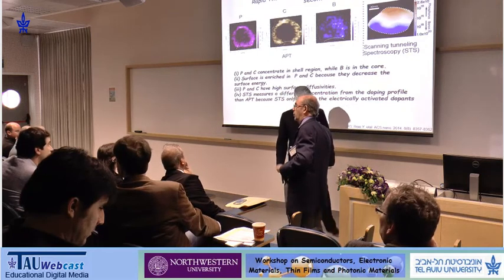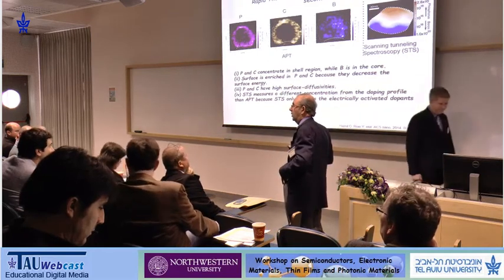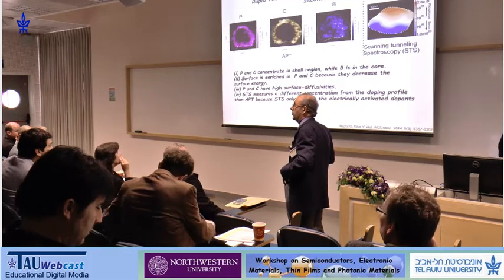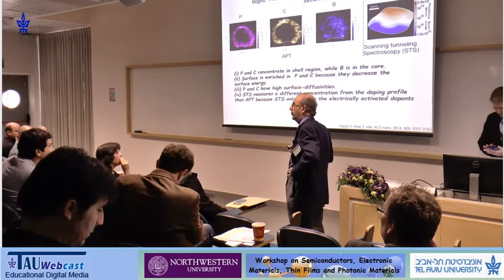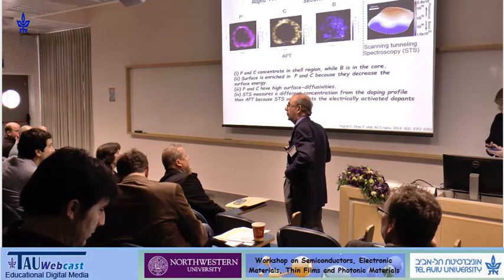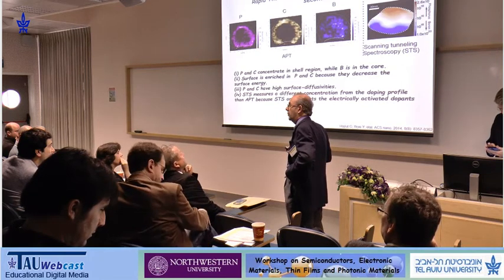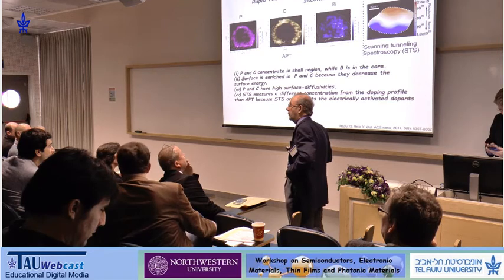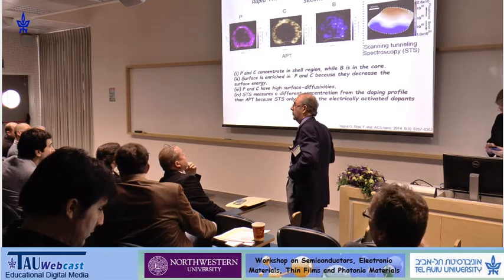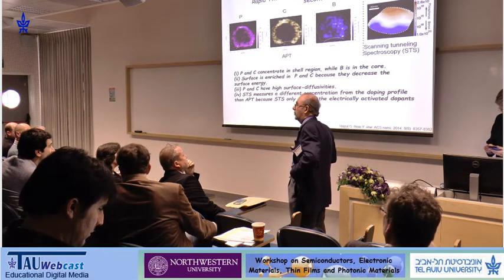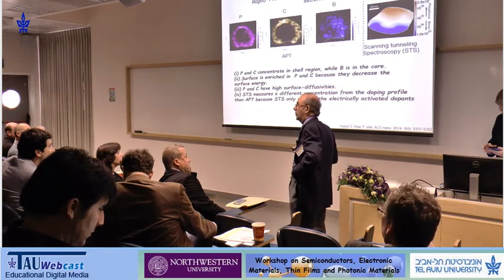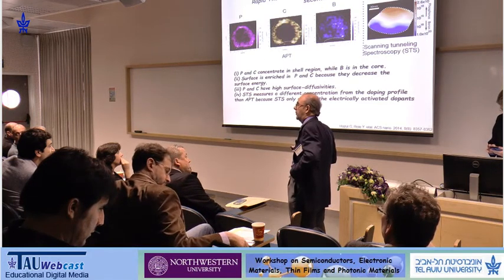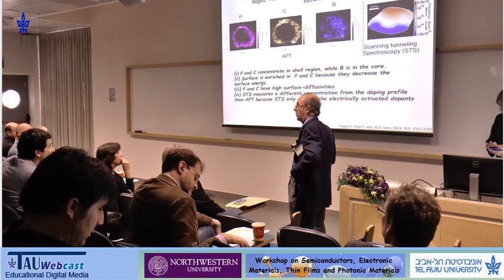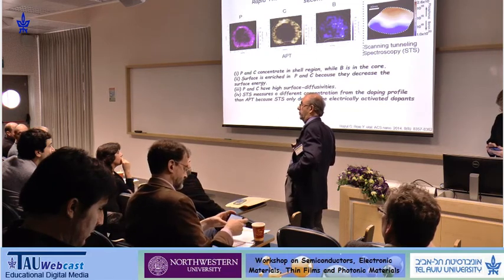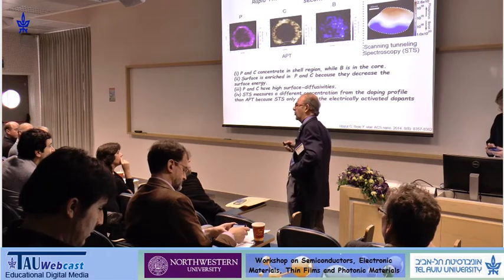I guess that carbon, we have carbon source from the preparation and also from the materials that we're using. So one way to test only the graphene would be by preparing a single-layer graphene made out of C13 atoms. That can be done slowly. So then you can be sure that you're testing only the graphene, that you have 100% graphene. Also, in answer to Mark's question, no one has looked on this scale before.